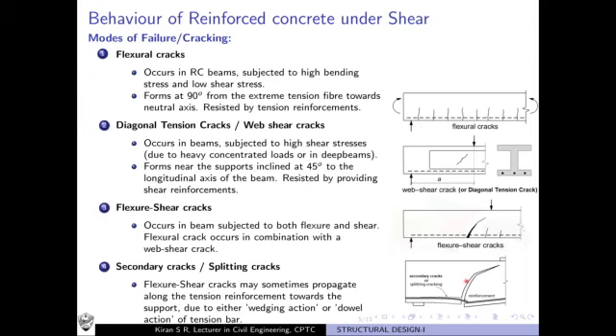There is one segment here and another segment on the right side of the crack. As the right side of the crack tends to move down, it tends to exert some stress through the reinforcement and tends to wedge the reinforcement away from the segment, and this results in a propagation of the crack, which is what is known as wedging action. What is dowel action? Dowel action is that as this segment moves down, it tends to pull the reinforcement away from the first segment, and that may also result in splitting of concrete closer to the tension reinforcement. So this we call a splitting crack or secondary crack.